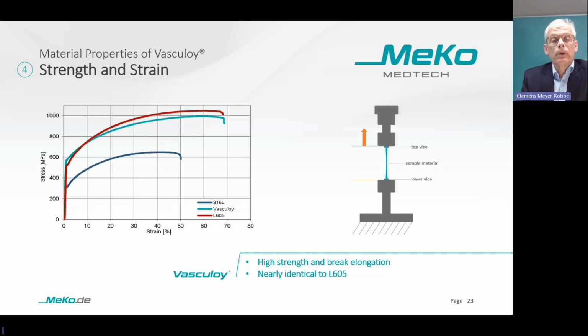First, everyone is looking for thin stent struts and a high deformability of the stent. That means we have to look to the strength and strain of the material. The strength and the strain are tested in tensile machines, where the material, here the stent tubes, are clamped and elongated with high forces. The elongation is plotted against the forces, respectively the stress. The diagram on the left side shows the stress-strain curves. On the y-axis, you see the stress, and on the x-axis, the strain.